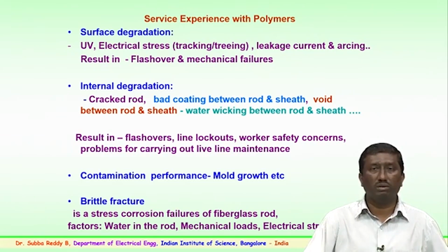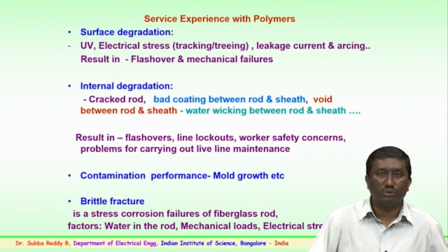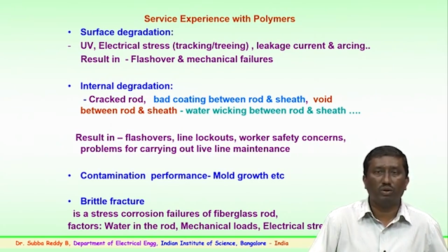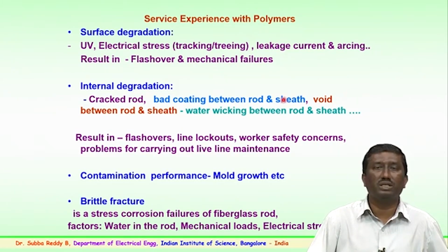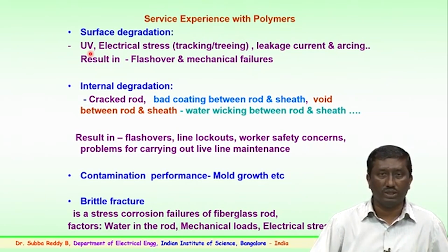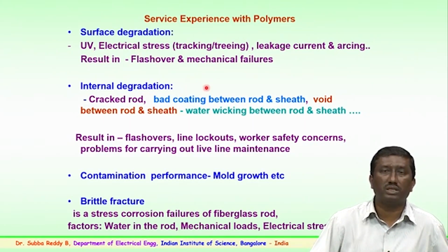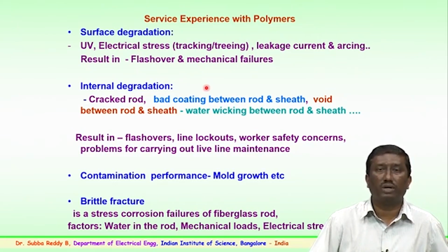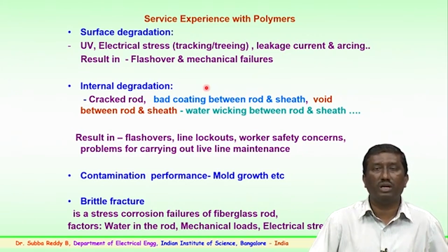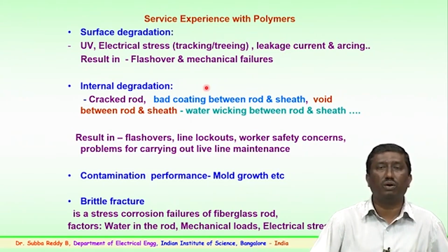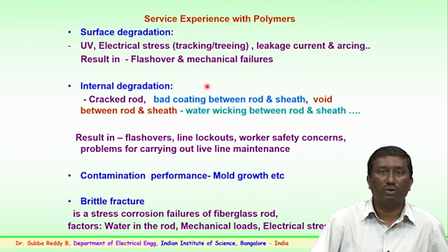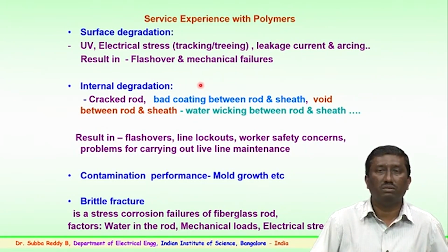So, we will look into the important aspects which a polymeric insulator or a non-ceramic insulator faces in the field. Surface degradation is the important aspect. The surface degradation may be caused by the ultraviolet rays from the sun, or from the corona of the hardware which we mentioned. Continuous electrical stress on the insulator over a period of time could cause tracking or treeing. Tracking or treeing is the slow failure of the insulator surface, where leakage current flows and the degradation of the material could happen.